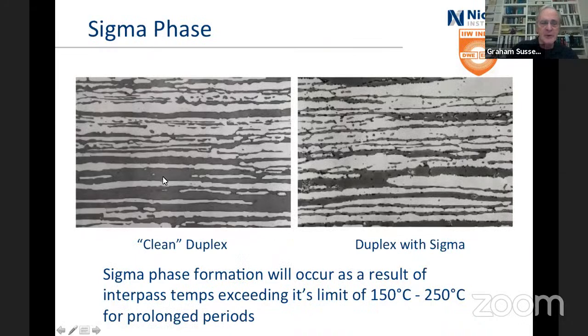And this is an example. Remember the picture we saw before? This is just a black and white of it, obviously, but here we've got the ferrite, here we've got the austenite, and nothing in the way of nasty bits and pieces. Here we've got a lot of them, lots of intermetallics. And it probably in this case occurred because the interpass temperature was above the 150 to 250 C for prolonged periods. So you just wound up with too long in the higher temperatures.